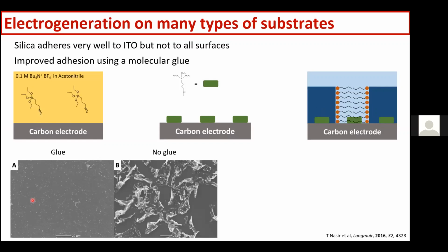And here is the SEM image of a film that used the APTES as a molecular glue, and you can see that we have a smooth and homogeneous film. The only reason we realize there is a film is because we have some silica beads on top. If we don't use this APTES layer to immobilize the film, you can see here that the film is not properly adhering, and here you see the bare glassy carbon with broken bits and pieces of the film. So it's really important to have this APTES layer to form the homogeneous silica film.